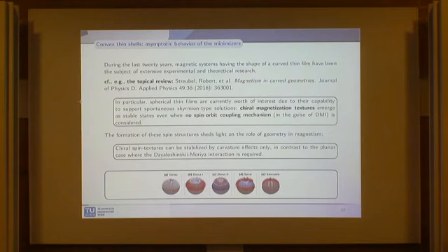As I told you, people are interested in the micromagnetic energy on curved thin films because you discover that for this geometry you don't need a minimizer with non-trivial topological degree. You don't need to take into account the Dzyaloshinskii-Moriya interaction. It's just the curvature that permits the spontaneous formation of magnetic skyrmions, meaning that this configuration will be stable, although maybe it is not the global minimizer of your energy function.